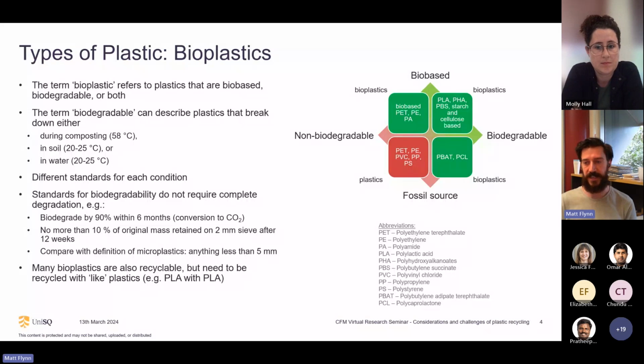Sometimes they're described as breaking down in soil or in water, and these are at more ambient conditions, 20 to 25 degrees. And these all have different standards. An example for the standards for composting biodegradation or biodegradability is they have to biodegrade by 90% within 6 months. So this is the polymer turning into CO2. 90% of the mass has to be gone within 6 months. And another criteria that they have to meet is that they must have no more than 10% of the original mass retained on a 2mm sieve after 12 weeks.